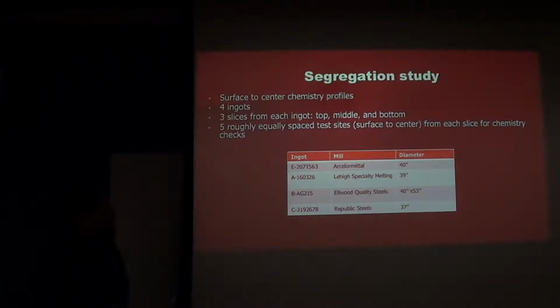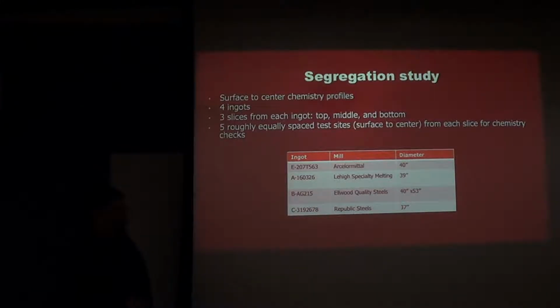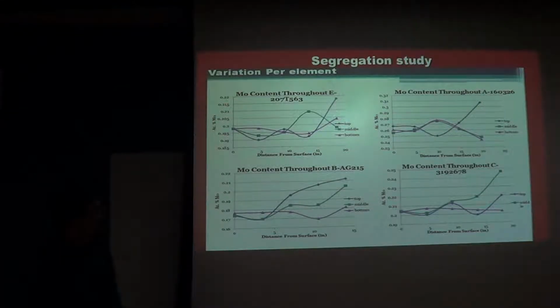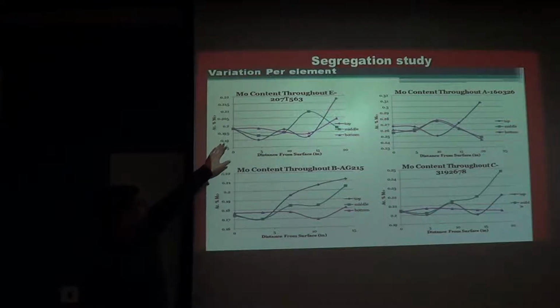So I had this study done where I took ingots of similar cross-section from several different suppliers, and in one case this had been forged out to a large square cross-section, a big billet. We cut slices out of the ingot at the top, middle, mid-height, and at the bottom, and then we evaluated the composition at 5 equally spaced positions from the surface to the center. And I have all the data of all the different elements that we looked at. I'm not going to show all of that, but just to show you the concept, if we look at the element molybdenum, we can see that we started off at near or just under 0.2 in this particular case,